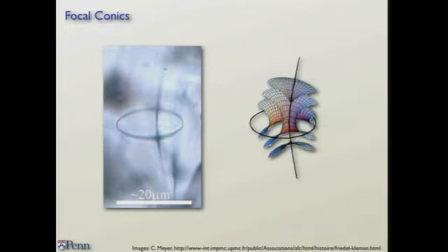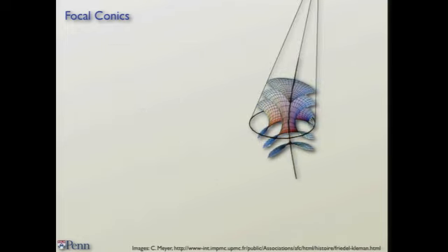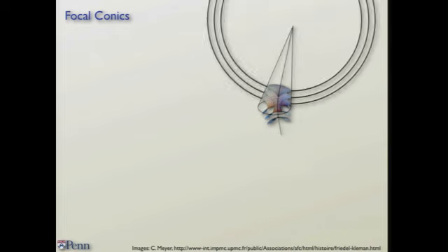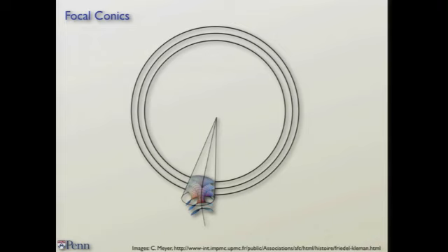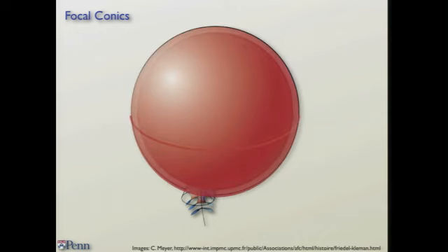And so here is a section of the focal conic domain, the insides. And I can take this section, see, all right, there's the data, there's the model. This part fits into a cone, okay? Here's the cone. And now what I can do is I can take this cone wedge and substitute a cone wedge from a sphere and swap them out. And because these surfaces come to this cone perpendicular to the surface of the cone, you can naturally put them into the sphere. And there's no cusp, it just fits smoothly. And so you can take a sphere and you can riddle it with these focal conic domains. The focal conic domains have negative curvature instead of positive curvature, and so it's quite possible that that would be favored depending on your energetics, right?